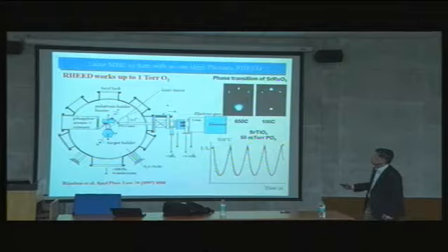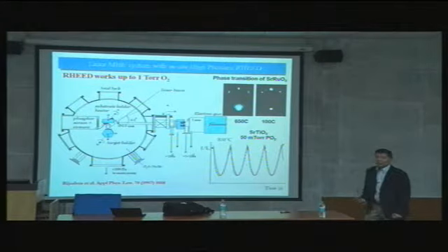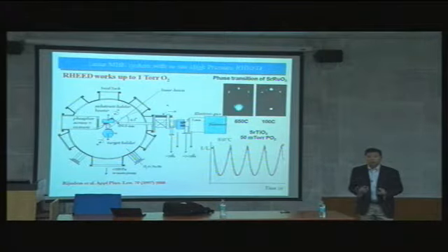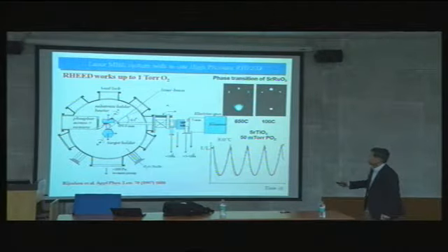And then your laser window brings in the krypton fluoride 248 nanometer excimer laser. That's the most popular laser used. Some people use frequency doubling or tripling of the YAG laser, making an infrared laser into a UV laser, and as the wavelength gets smaller, the energy density goes up. But I think different sources of laser can be used.